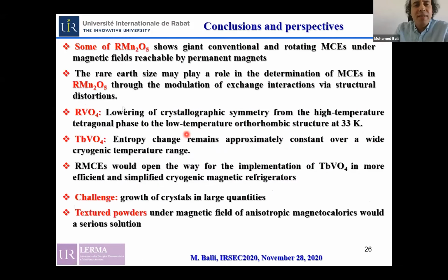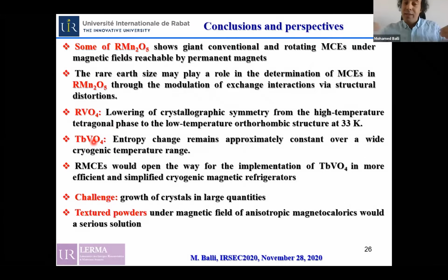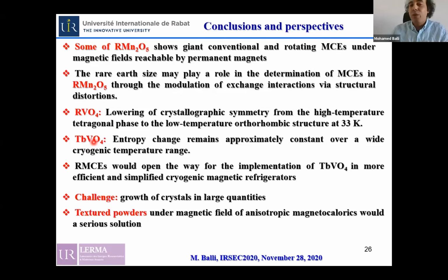As shown in this presentation, some of the rare earth manganese and rare earth vanadate compounds involve excellent magnetocaloric properties at cryogenic temperature range, opening the way for their application in the liquefaction of hydrogen and helium, for example. Particularly, the terbium vanadate compound involves a large magnetocaloric effect over a wide temperature range, which is highly appreciated from a practical point of view, particularly when using AMR and Ericsson cycles.